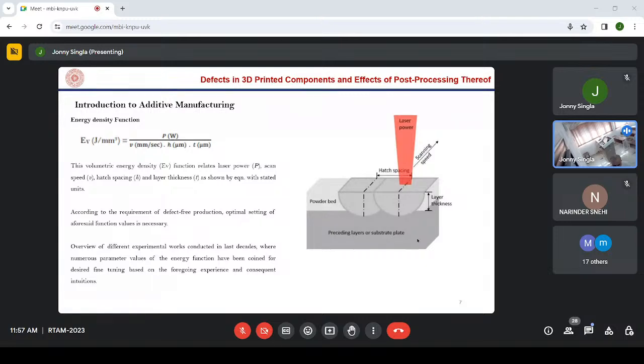And this is the layer thickness. How thick a layer you are depositing in each surface scan. And then hatch spacing means between two scans, what is the difference between these two? That is your hatch spacing, right? And then what is the power of the laser source? All these four parameters put together in this relation will define the energy density function.